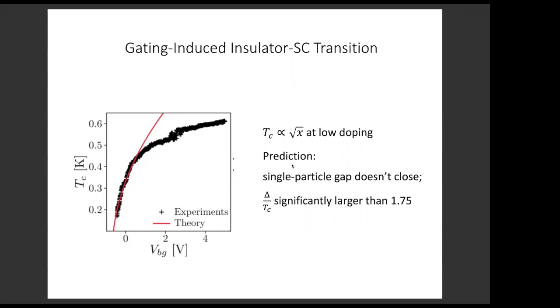And then our theory would also predict that the single particle gap should not close, and the delta over Tc should be significantly larger than the BCS value. So these can all be verified by future STM experiments.